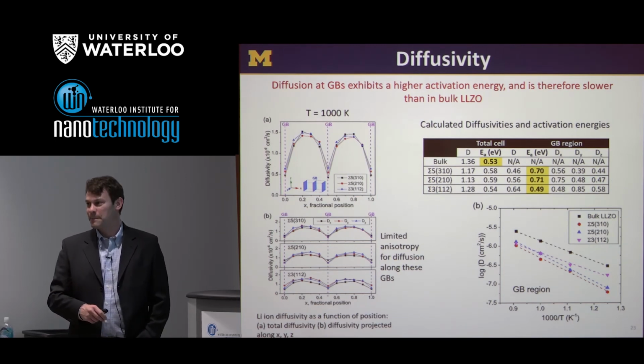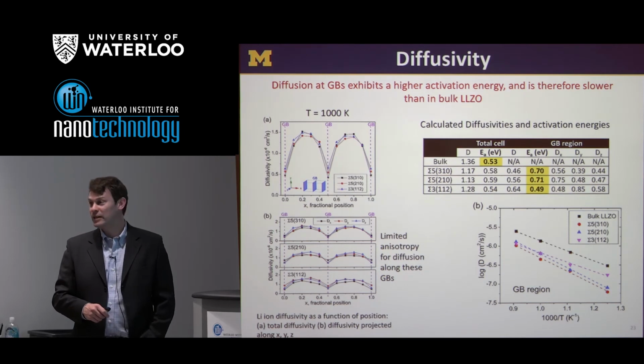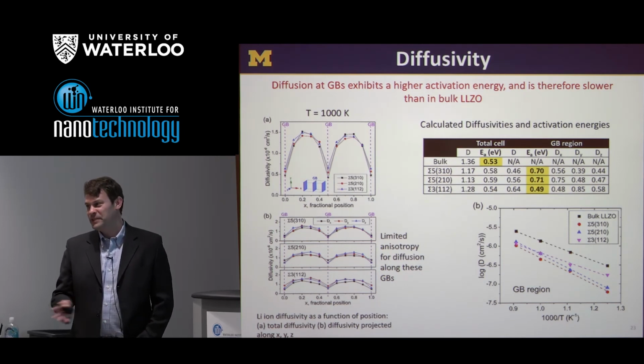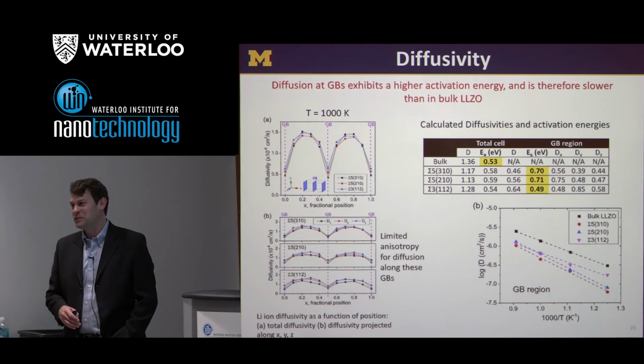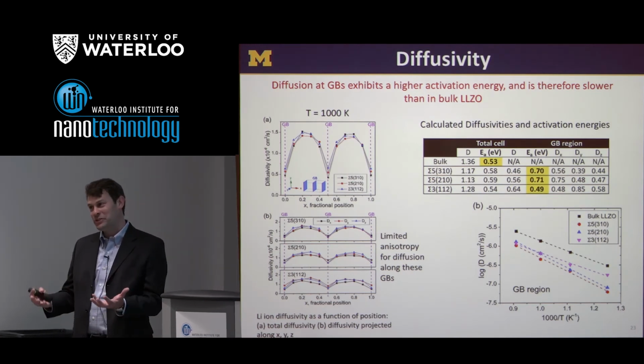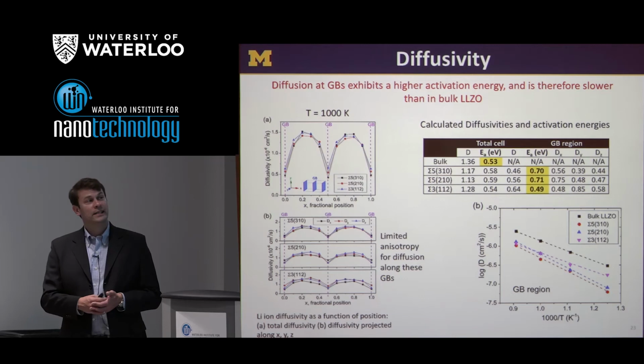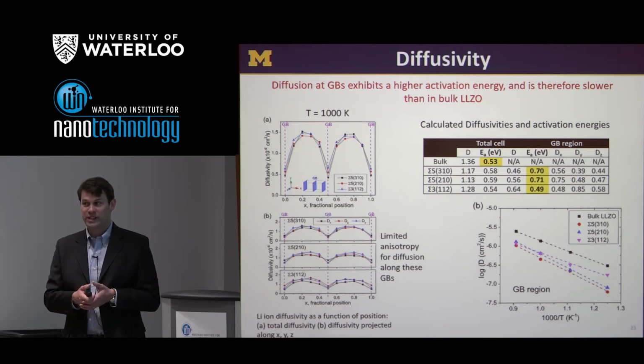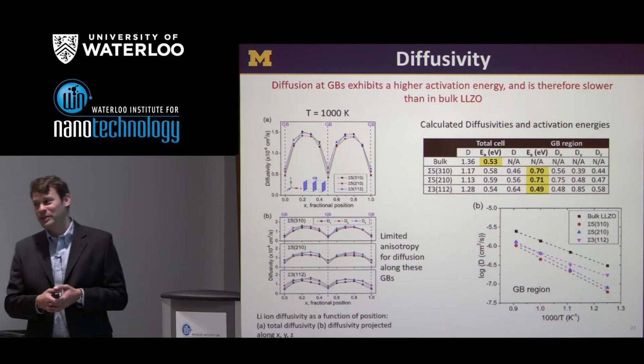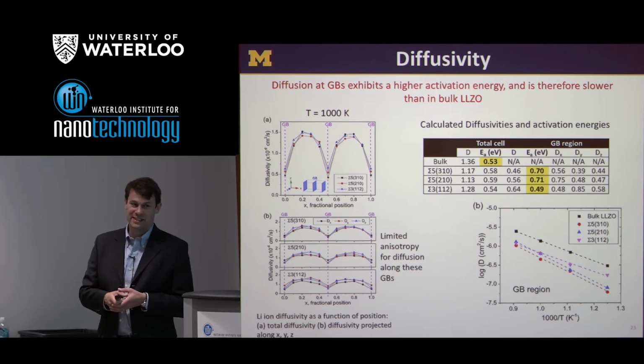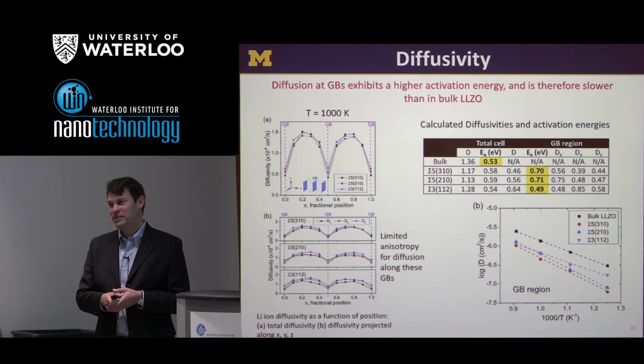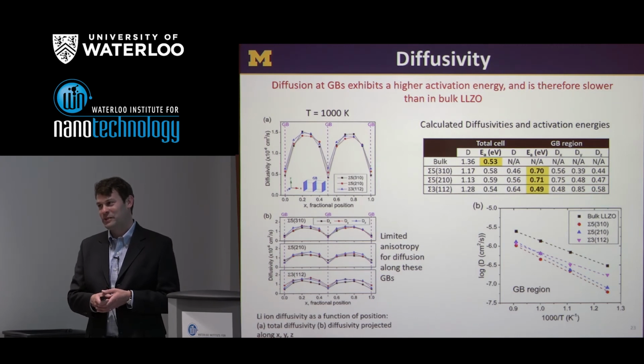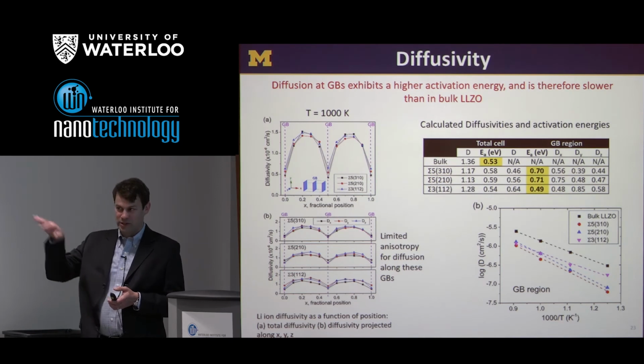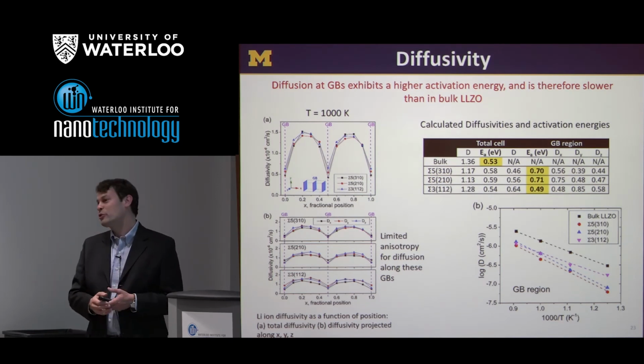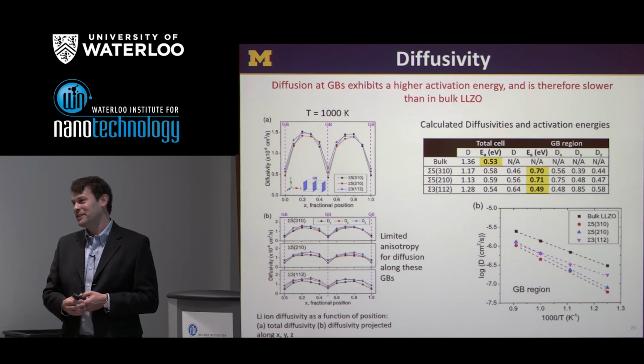The diffusion coefficients then would be really, really low. Yeah, and again, in concert with experiments. This is sort of a typical failing of an interatomic potential. You can simulate big systems, but you maybe lose some accuracy. The other way we could do this calculation would be with density functional theory and ab initio molecular dynamics. But in that case, you might get, say, a few picoseconds of MD time, and the statistics associated with the mean square displacement would become very poor. So here we get very nice linear mean square displacement plots, but with some trade-off perhaps in the accuracy of the activation energy.